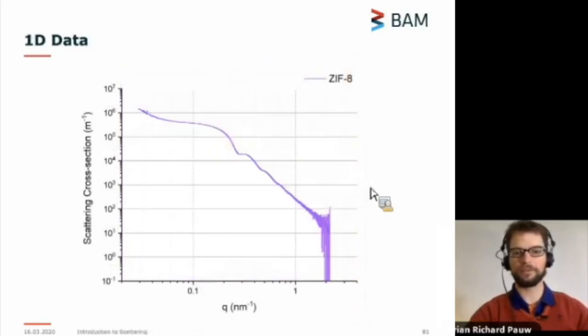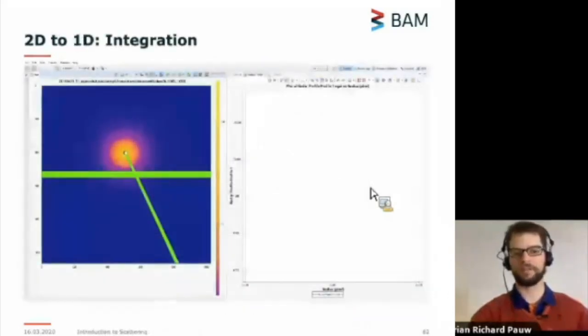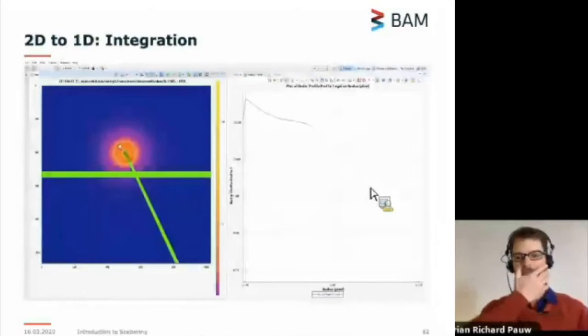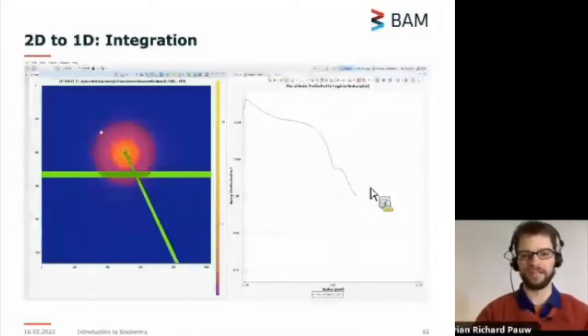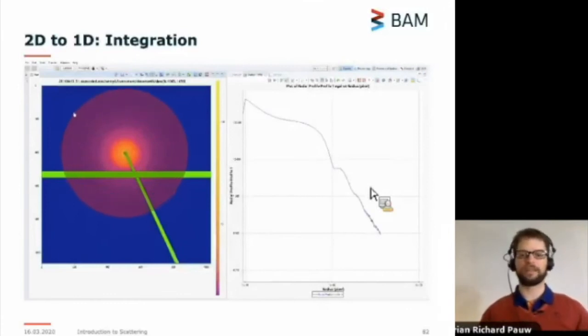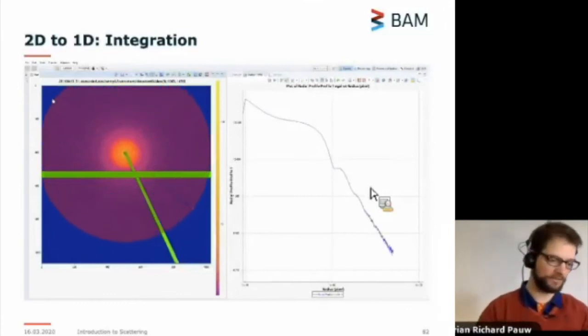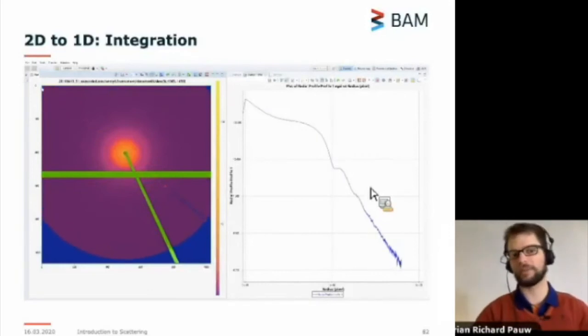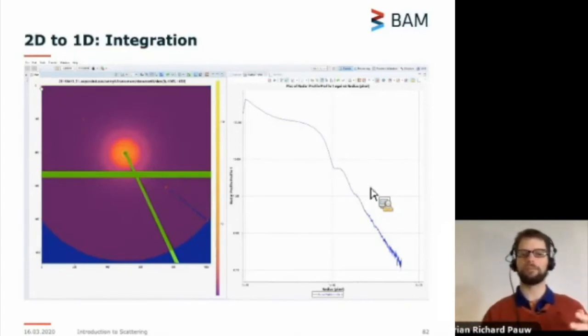So the further out we go from the center of the scattering pattern, the more our intensity decays, but it doesn't really change with the azimuthal angle over here. The good thing about this is that the further out you go, the more pixels there are that cover this angular range. So while the intensity drops off very, very fast, the statistics don't deteriorate all that much because we've got more pixels to average over.